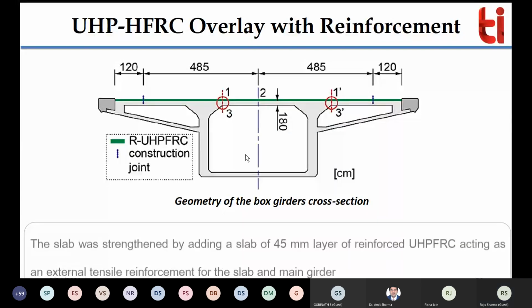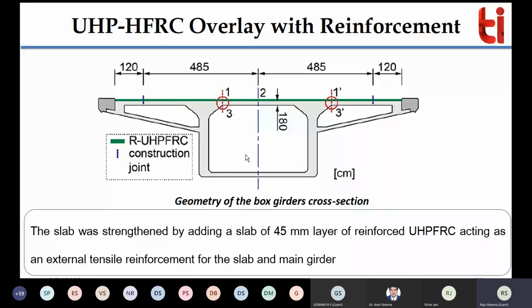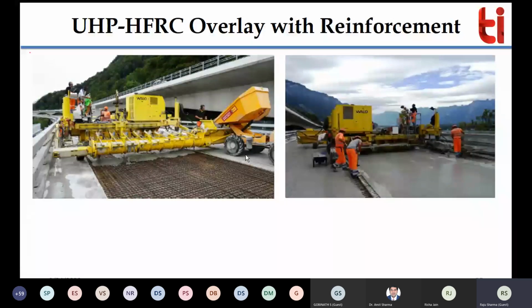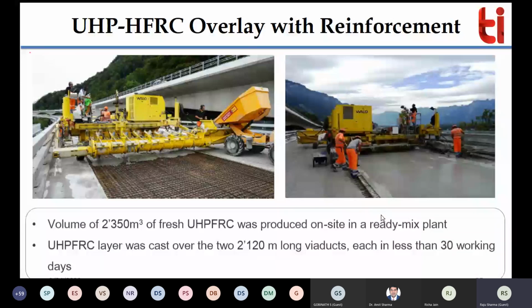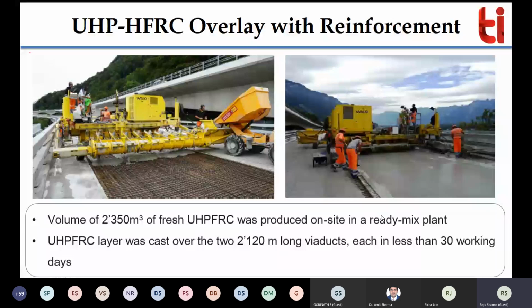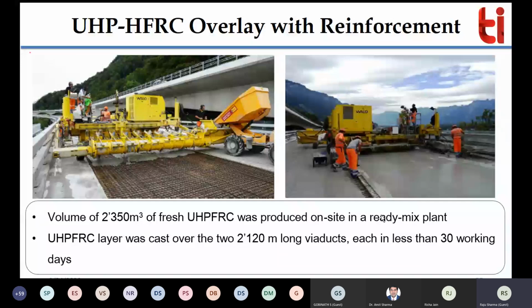And the new slab is laid with a 45 mm thick layer, right? In this image on the left side there is the reinforcement and UHPFRC is laid on that, and then on the right side you can see the finishing of that slab. The total volume was 2350, and they did it with ready mixed concrete, and the UHPFRC layer was cast over the 2120 meter long viaduct in less than 30 working days. So they have done a wonderful job using UHPFRC to retrofit the bridge deck.